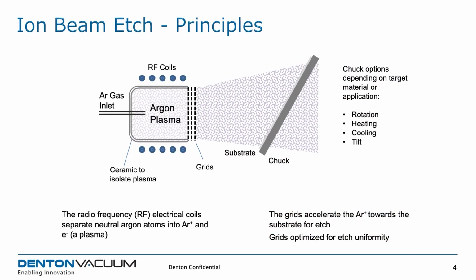So here's a diagram of how an RFICP source works. In the center is a quartz discharge chamber that contains the plasma. This is advantageous because the plasma is fully remote from the substrate, which means it's unaffected by anything that's going on by the etching. The result is that even if you etch on time alone, you get repeatability of better than 1%.